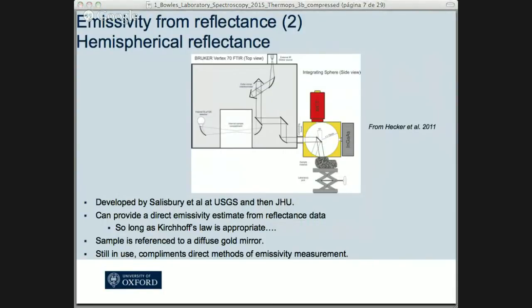The other method, which was really pioneered by people like Jack Salisbury at USGS and then Johns Hopkins University, and has been used by lots of other people subsequently, is to, rather than worrying about preferential scattering of angles, which happens in the ellipsoidal or biconical reflection setups, where you can get polarization effects, I mean, if I go back quickly, you can see some pretty seriously fast mirrors going on here, and that will have orientation effects in your spectra. So the other option is to stick your sample up against an aperture in a gold diffuse integrating sphere, measure the diffuse reflection coming off of the sample, and then collect a small sliver of that energy from the 2π geometry.